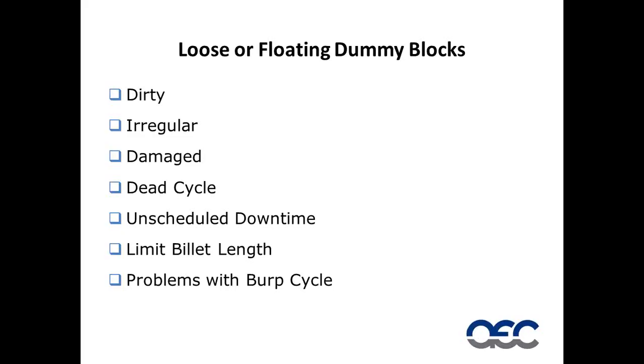They cause unscheduled downtime because often the dummy block isn't put in front of the stem and you actually push the ram into a hot billet. They typically limit the billet length that we can use in a container. When we use a fixed dummy block, we can use a longer billet for each extrusion. It also becomes extremely difficult or maybe impossible to have a burp cycle. With a burp cycle with a fixed dummy block, we hope that it will relax and be reduced in diameter during the burp. And with a loose dummy block, this is impossible.